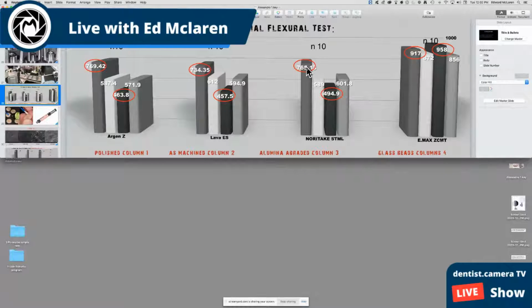Okay, you're not going to polish the inside of your crowns, are you? I don't. First of all, you don't have the instrument shapes to do that. I'm going to use as machined. What comes out of the machine? Maybe sandblasted, maybe not. So we tested as machined. So we made some discs, as machined, fractured them, as machined, fractured them, as machined, fractured them. Biaxial flexural. Okay, so what that tells me is, and I did 6 or 7 other materials, all right around 600 megapascals, plus or minus, the applied strength, the actual strength of the material is around 600 megapascals, as we use it anyway. And if we sandblast it, it goes down to under 500.